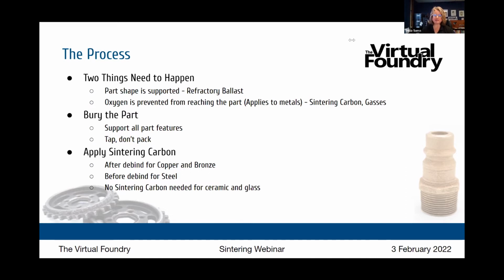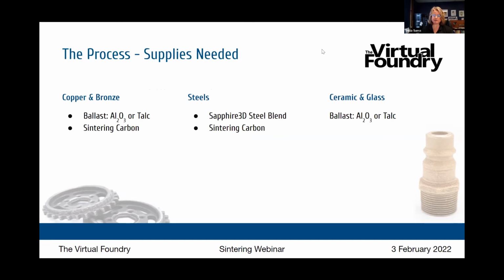And then once all of that is loaded, you'll apply the sintering carbon to the top of that. When the sintering carbon is applied is dependent on the material that you're working with. So sintering carbon is applied after the debind is completed for copper and bronze. Sintering carbon is applied at the very beginning of the process for steel. And then there's no need for that sintering carbon for ceramic and glass, since they are not so sensitive to oxygen. So let's look at exactly what you need for each material.